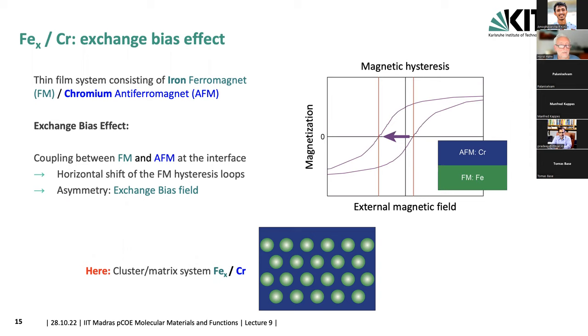So we built a thin film, which consists of iron, which is a ferromagnetic material, in chromium, which is an antiferromagnetic material. And what you get if you do something like that, for example, in a thin film where you have a layer of iron, no clusters here, but a layer of iron and a layer of chromium, you can even build it up as multilayers, you get an exchange bias. So these magnetic layers are interacting with each other, and you can see that the hysteresis loop is shifted to one side. This is called the exchange bias field, which describes this interaction of the two layers by the different magnetic properties. What we wanted to see is, when we introduce iron clusters into the chromium, what kind of behavior we would obtain. The result is nice, but it's not spectacularly different, I should mention.